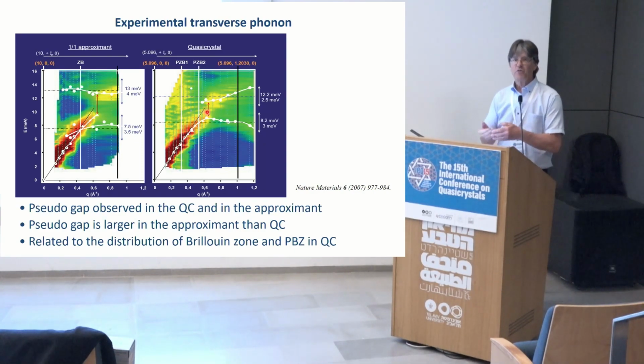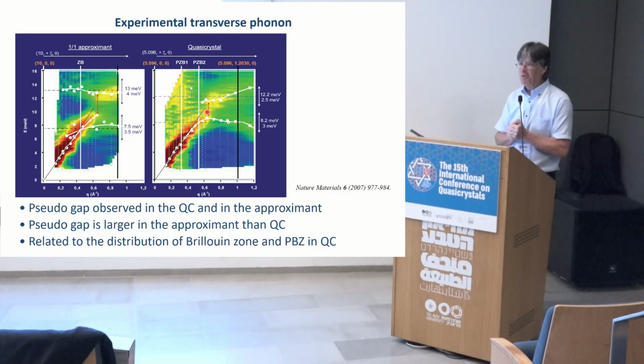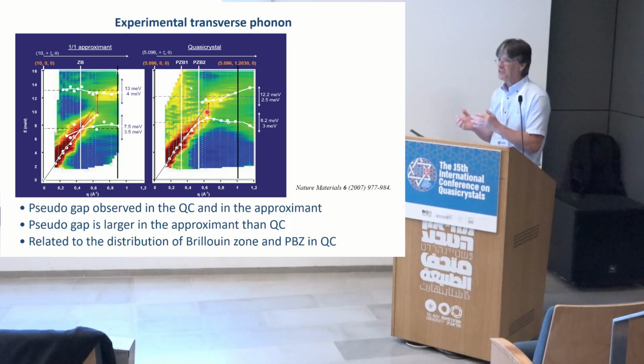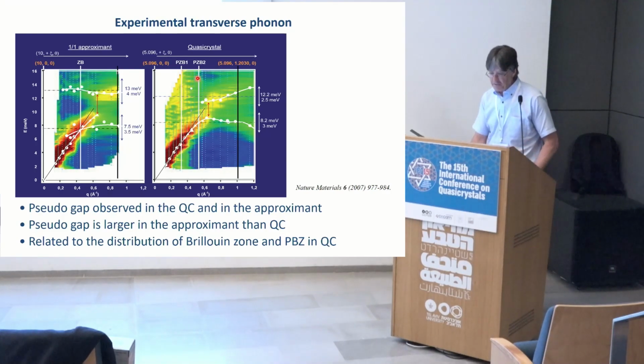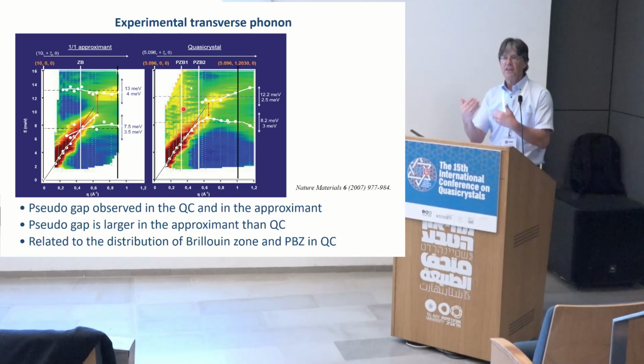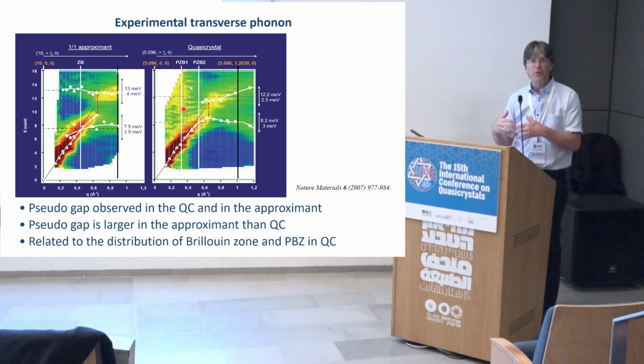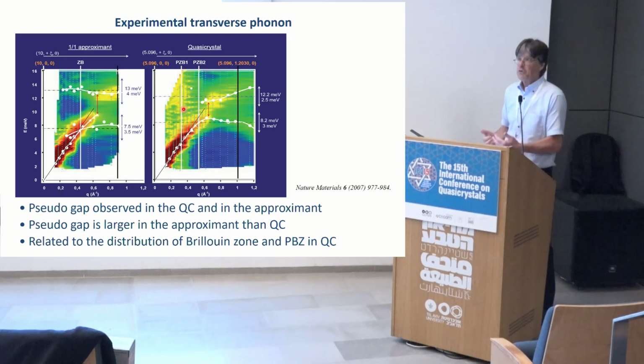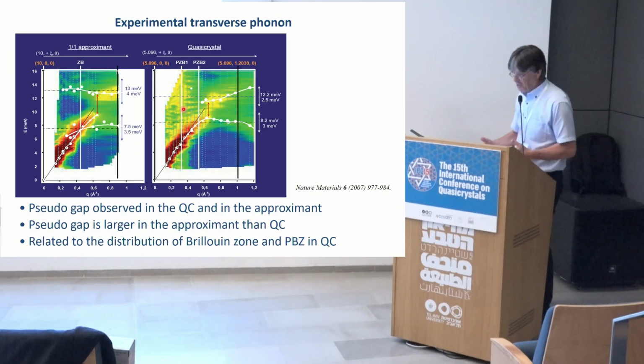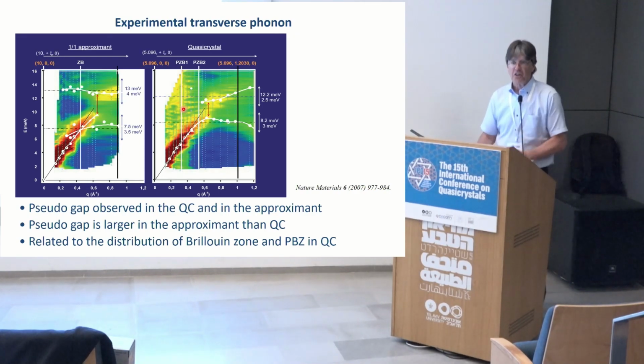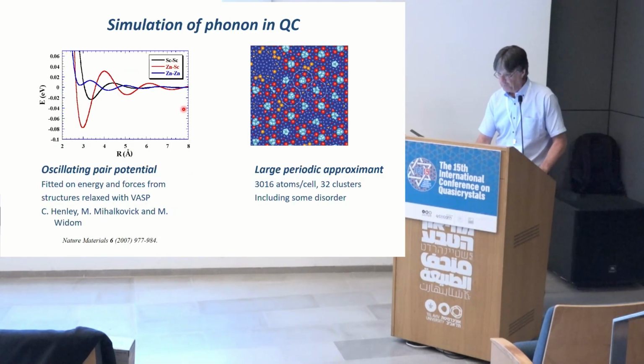At first, if you look from far, it's a bit disappointing. It's almost the same in the 1-1 approximant and in the quasicrystal. The only thing we can say is, okay, here we have two zone boundaries. We can use this scheme of pseudo-zone boundaries to interpret our data. But I would say it's a bit disappointing. We don't have any clear-cut trace of the quasi-periodicity.